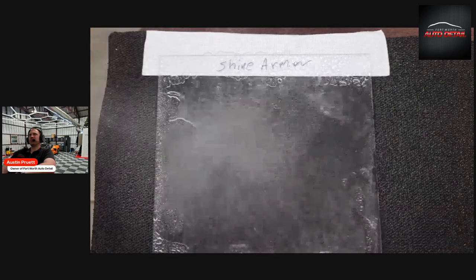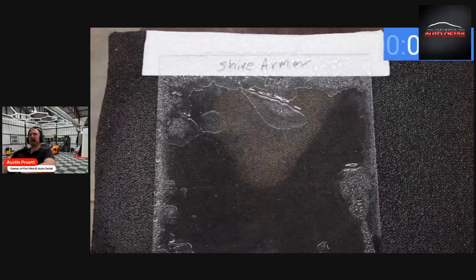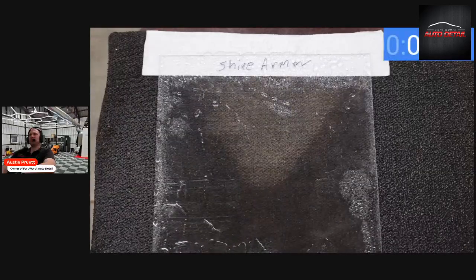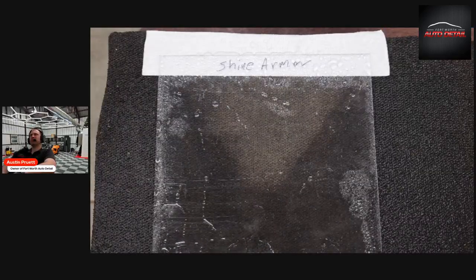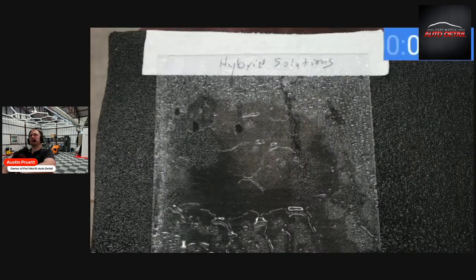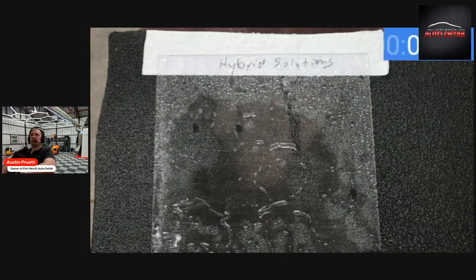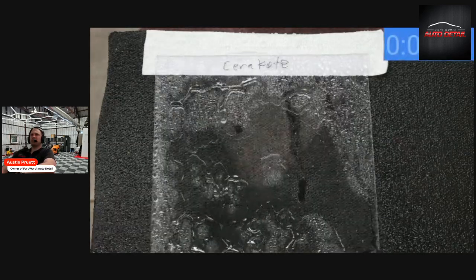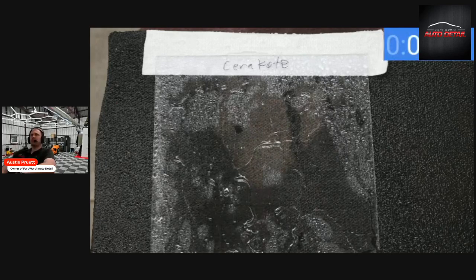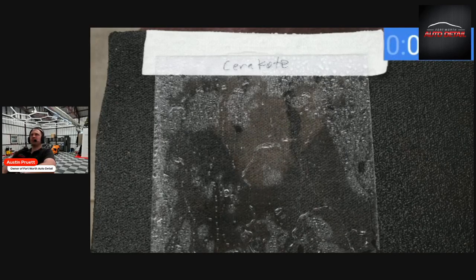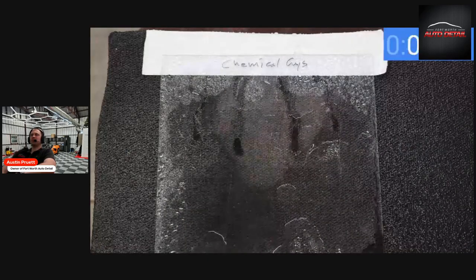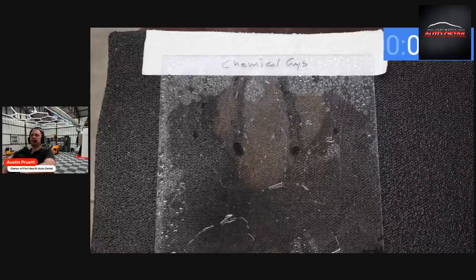And 4.5 hours of warm and hot water spray took its toll on the Shine Armor. About 13 seconds for the sheet of water to completely dissipate. A much smaller sheet of water formed on the Hybrid Solutions and cleared in only 4 seconds. The Cerakote performed very close to the same as the Hybrid Solutions, and the water dissipated in close to 5 seconds. And the sheet of water on top of the Chemical Guys cleared up in about 7 seconds.